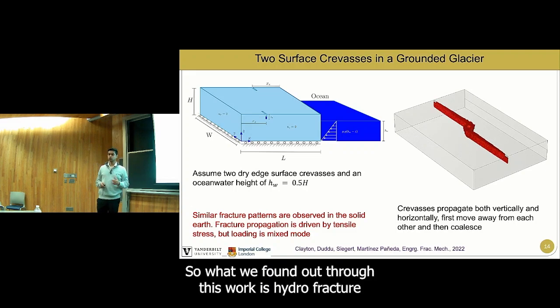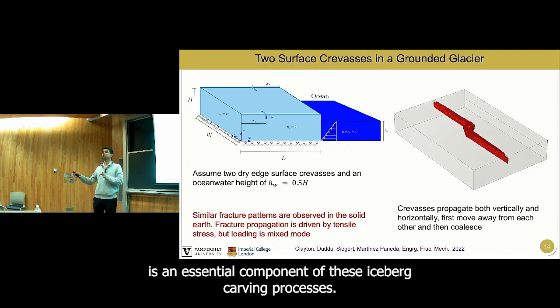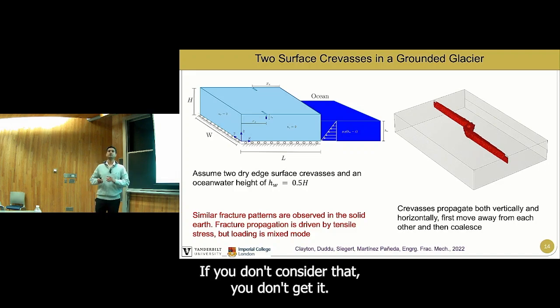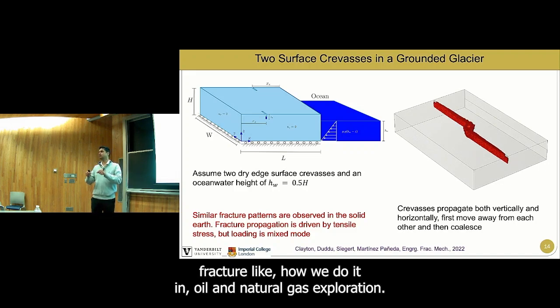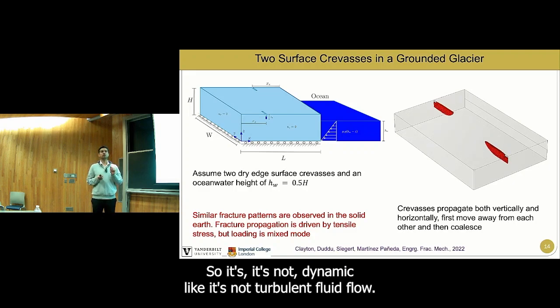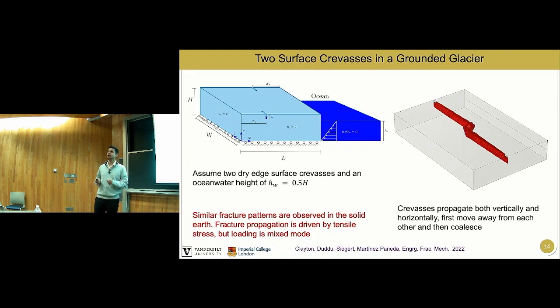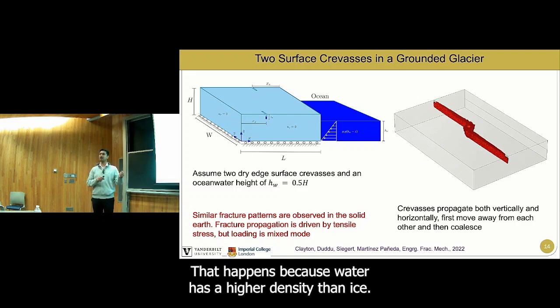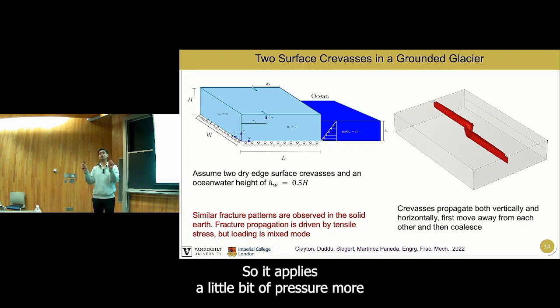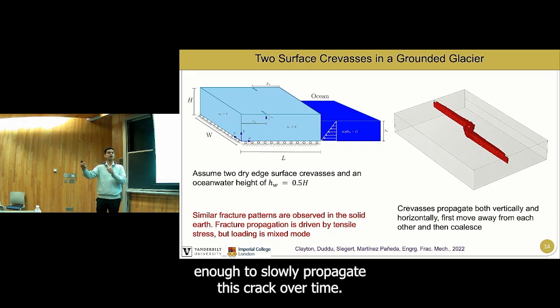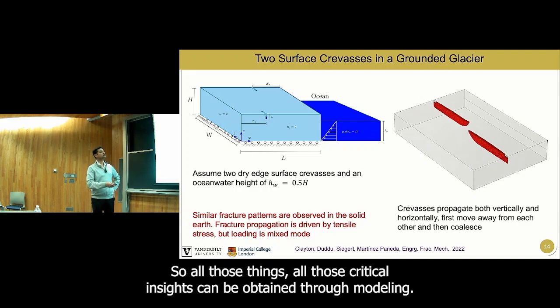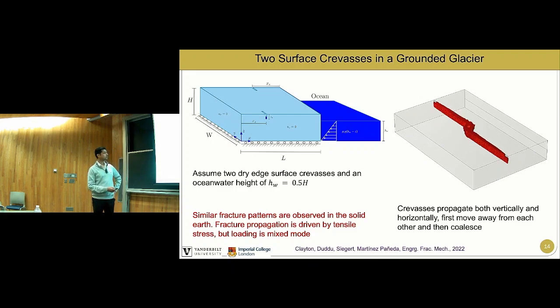So what we found out through this work is hydrofracture is an essential component of these iceberg calving processes. If you don't consider that, you don't get it. And it's not hydrofracture like how we do it in oil and natural gas exploration. So it's not dynamic, like it's not turbulent fluid flow. It's just slow water-based fracture that happens because water has a higher density than ice. So it applies a little bit of pressure, more than the closing ice pressure, enough to slowly propagate this crack over time. So all those critical insights can be obtained through modeling, right?